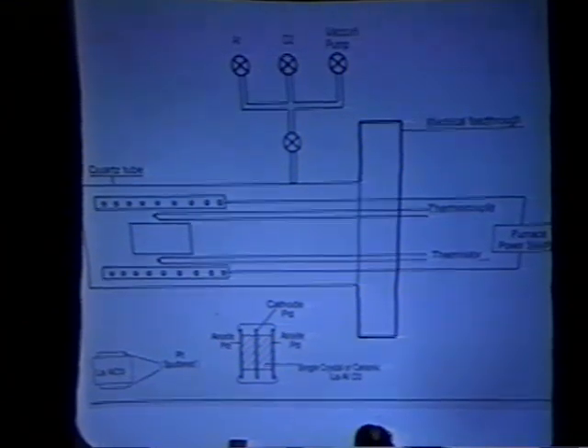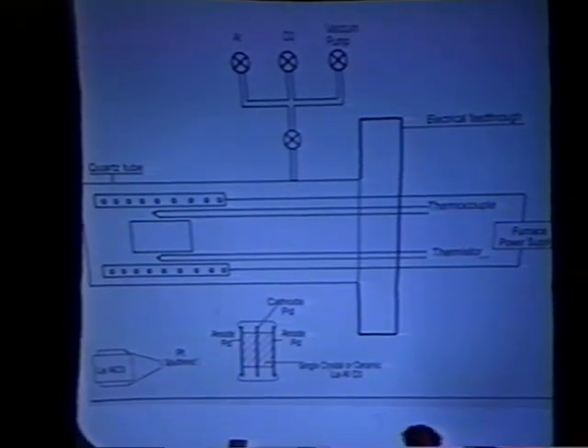So those crystals are red when you start, but when you load them with deuterium, they turn white. That's an easy experiment to do, it's reversible, you keep them in air, they go back to red. So here they are, we used 2 of them, and to have a good contact, on top of this sample, we deposit platinum or palladium. Recently we tried platinum. We're not sure if there's an influence or not of this deposit. If platinum is important, palladium can do the same thing, we're not sure. We tried it for a blocking interface. So platinum might hopefully block the deuterium from getting out of the crystal. So we use platinum in this experiment I'm going to talk to you about.